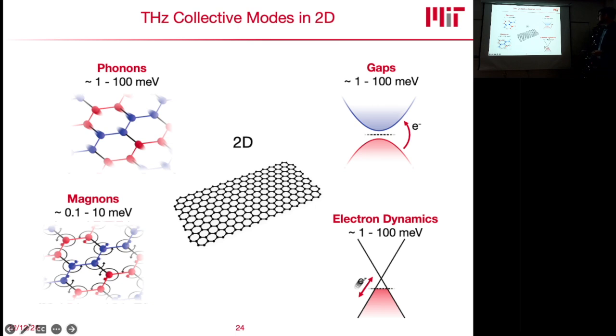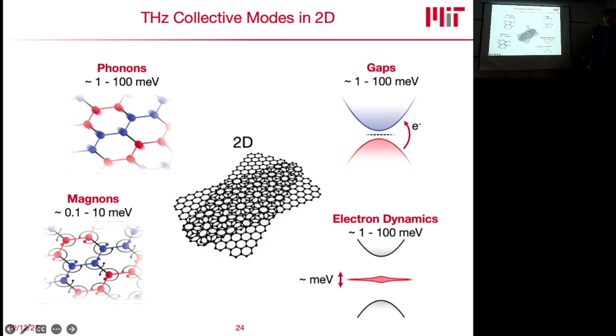On top of that, most of the electronic dynamics in these materials also evolve on terahertz timescales and at milli-electron volt energies. Where this becomes even more dramatic is if you go from one material to heterostructures of these materials, what people like to call moiré engineering, where the kinetic energy of your electrons is being quenched due to destructive interference in these moiré lattices, and you start generating flat bands. These flat bands then host electrons with kinetic energies of milli-electron volts. So now all of your degrees of freedom start becoming on the order of milli-electron volts and start becoming correlated. This is why I take all of this as a motivation that engineering and looking into terahertz light-matter coupling in these materials is extremely important.